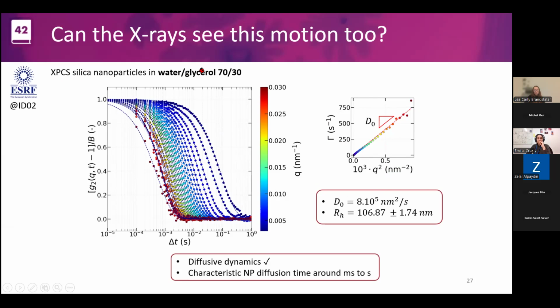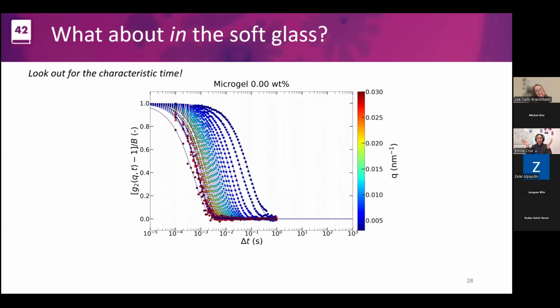Everything is looking great. So here, compared to the previous slide, which was water, now we're doing it in water and glycerol, which is the solvent I used to swell my soft glass. So we see that we get pretty much the same hydrodynamic radius. Nevertheless, the diffusion coefficient is a bit different, but that depends on the viscosity of the solvent as well, so that is normal. We do have diffusive dynamics, meaning that we have a scaling, like I showed in the previous slide, of gamma versus q squared, that's giving the slope of the diffusion coefficient, which is typical characteristic of Brownian motion.